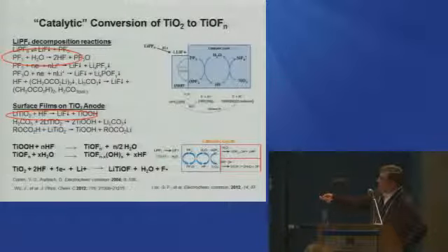But then once you've made HF, that HF can do a lot of different things. It can react with the lithium to make lithium fluoride, which is basically an insulator, and block electron transfer across the interface. It can get trapped into these other types of products, lithium carbonates, for instance. But what we noticed was that if you actually generated HF, you could actually start to make surface hydroxyls due to this exchange process.